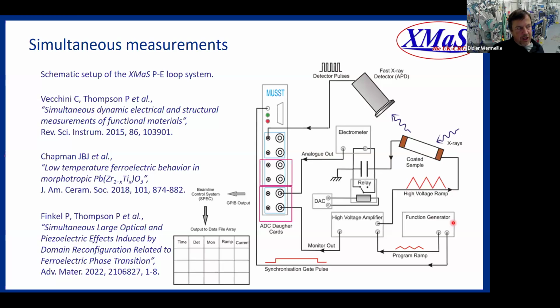We've also used the ESRF ZAP scan, so the fast scan for spectroscopy, for a few months now, using also the MUSST card and the signal from the monochromator, so we can go much faster with our spectroscopy with XMaS, especially XMCD measurements, instead of the traditional step-by-step measurements that we were doing until recently.